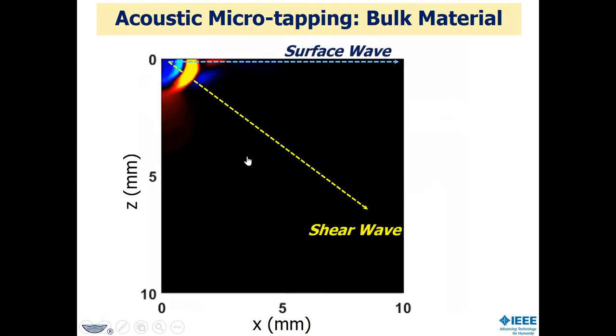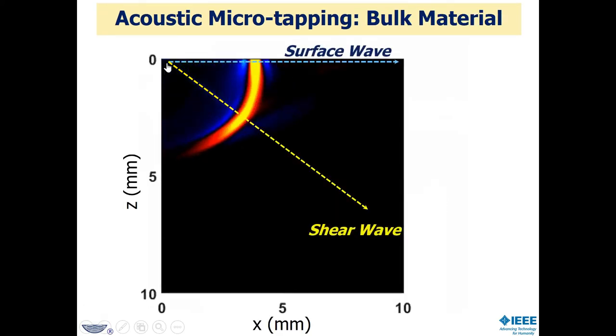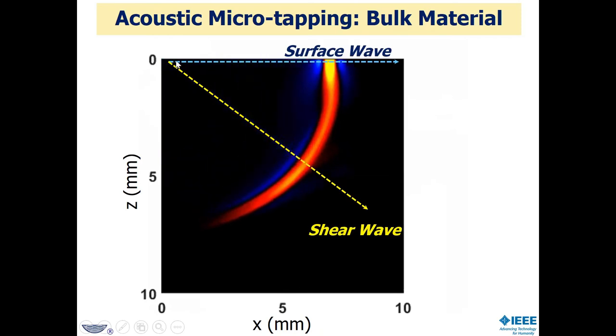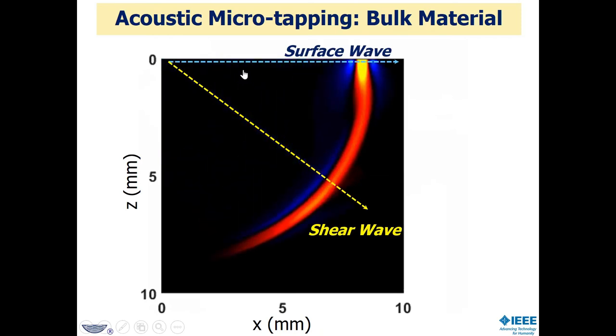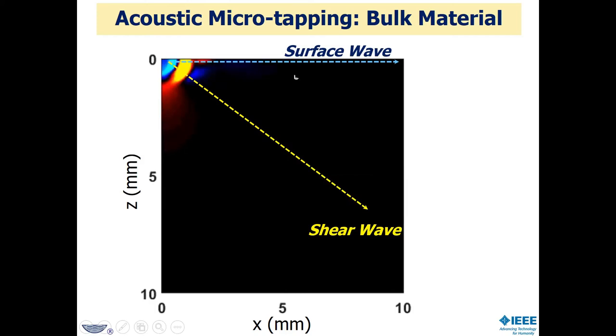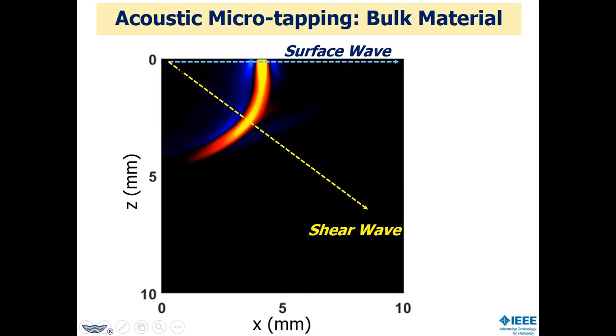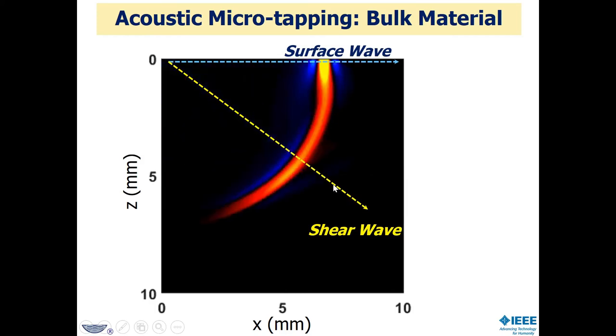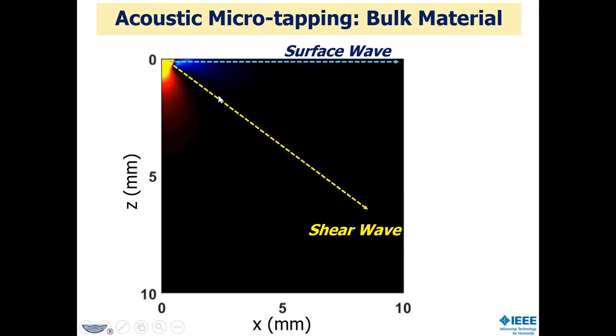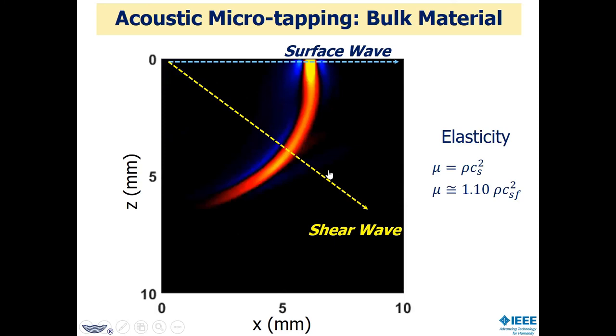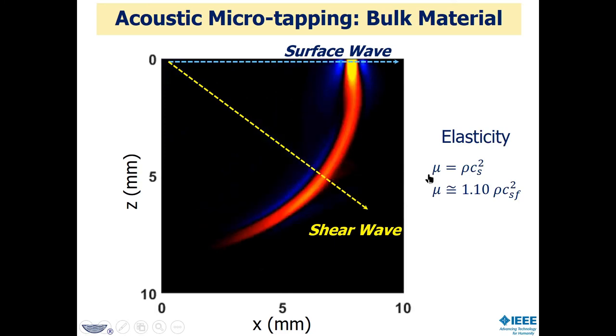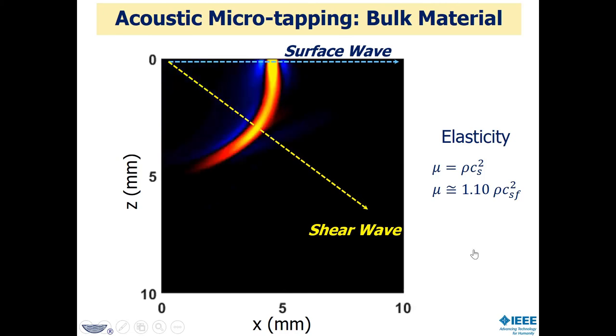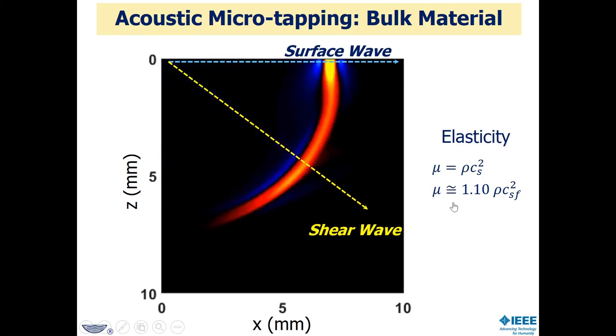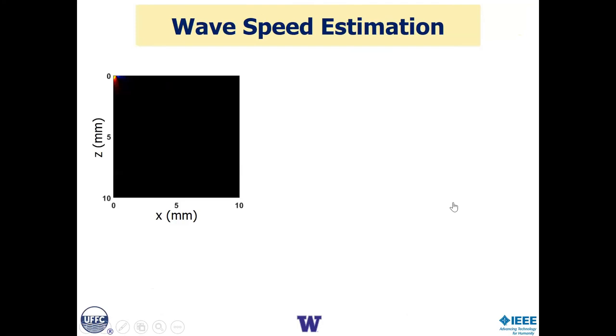This is just a simulation, but it shows what happens. If we hit right here into a conventional soft material, such as tissue, we'll launch two waves. One is a surface wave along here, a Rayleigh wave. The second is a bulk shear wave coming off at a fixed angle, pretty much a constant angle for all soft tissue. As we expect, this relation between the shear elastic modulus and the wave speed squared has a little fudge factor for the surface wave, but nonetheless, it very closely matches that simple idea for quantitation.